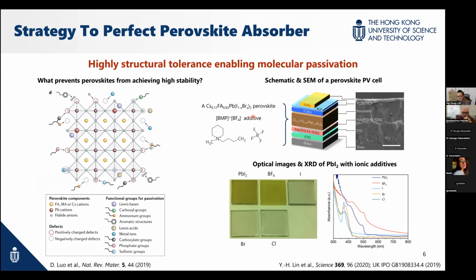But as you can see here, it contains a cation and an anion. And the anion is of a size comparable to the X site in a perovskite. But I think so far no one has found that this kind of pseudo-halide forms part of the perovskite structure. But this kind of large cation cannot go into the perovskite structure. What happens is that it will be pushed out of the crystal structure.